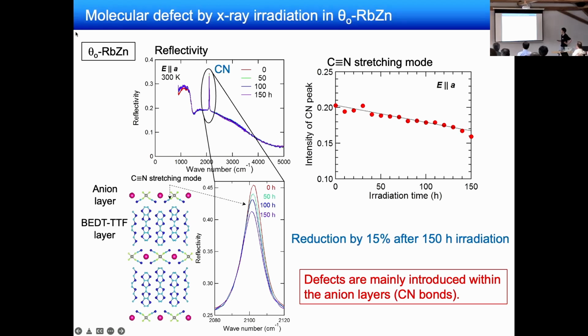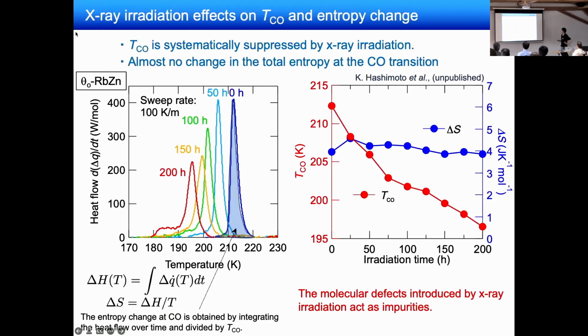Okay, then we measure the DSC. We perform the DSC measurement for the X-ray irradiated sample, and we found that the charge order transition temperature is systematically suppressed by X-ray irradiation like this. And actually, the charge order transition temperature decreases almost linearly with the irradiation time. But the entropy change at the transition does not change with irradiation. So this indicates that there is no phase separation by X-ray irradiation.